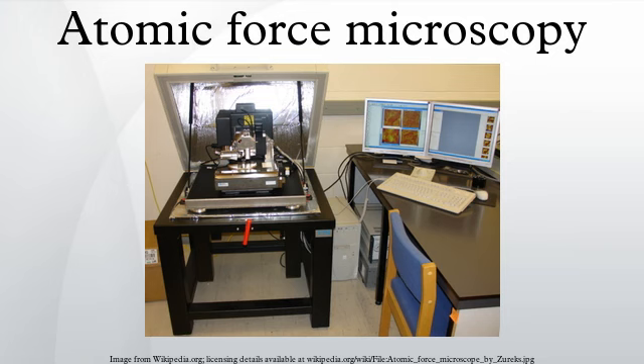In dynamic modes, information about the cantilever vibration is monitored in addition to the static deflection. Problems with the technique include no direct measurement of the tip-sample separation and the common need for low-stiffness cantilevers, which tend to snap to the surface. These problems are not insurmountable. An AFM that directly measures the tip-sample separation has been developed. The snapping can be reduced by measuring in liquids or by using stiffer cantilevers, but in the latter case a more sensitive deflection sensor is needed. By applying a small dither to the tip, the stiffness of the bond can be measured as well.